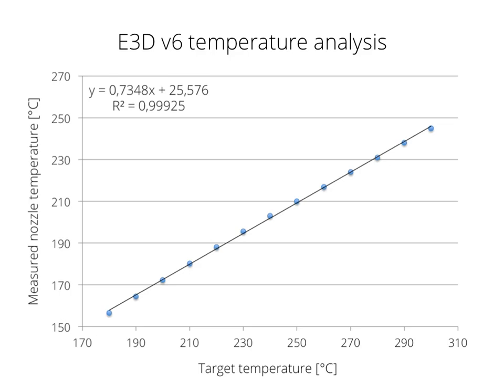So I used a thermocouple which was 3 millimeters in diameter and put it down into the shaft of the E3D V6 hot end until it reached the nozzle, and measured then the nozzle temperature as such. I started with 180 degrees and measured an actual nozzle temperature of around 156, and then started to increase the target temperature by 10 degrees, but actually got only an increase in nozzle temperature of around 7 degrees. So this means that when you reach 300 degrees Celsius as a target temperature, you actually just got a nozzle temperature of 245.